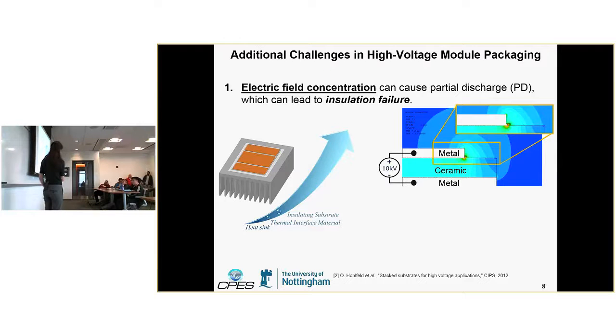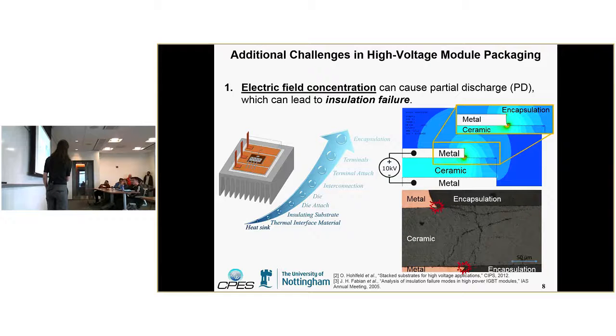So you've got your metal substrate. If you apply, for instance, 10 kV across this, you can see that in the bulk of your ceramic, the electric field is pretty uniform, and it's exactly what you would expect: your voltage over your distance. But where your metal, ceramic, and encapsulation meet, the encapsulation being, again, for improved dielectric properties, that's where you get your significant electric field concentration. That's called the triple point, and that's where your partial discharge will occur. This is an example of a real metal, ceramic, metal substrate, where repetitive partial discharge was occurring at these triple points, and it actually led to cracking of the ceramic.